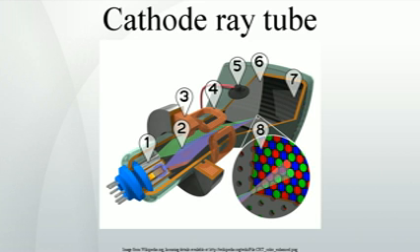Most color CRT displays, that is television sets and computer monitors, each have a built-in degaussing (demagnetizing) circuit, the primary component of which is a degaussing coil mounted around the perimeter of the CRT face inside the bezel. Upon power-up of the CRT display, the degaussing circuit produces a brief alternating current through the degaussing coil which smoothly decays in strength, fades out, to zero over a period of a few seconds, producing a decaying alternating magnetic field from the coil. This degaussing field is strong enough to remove shadow mask magnetization in most cases.